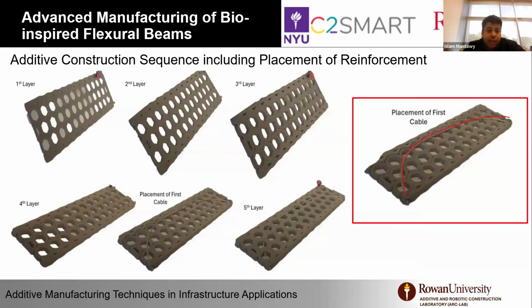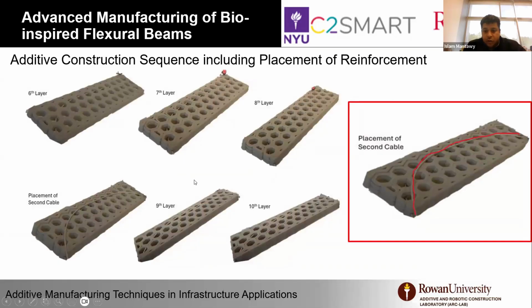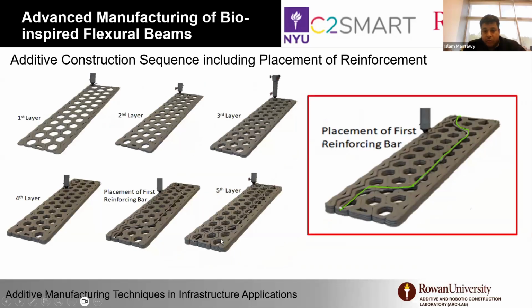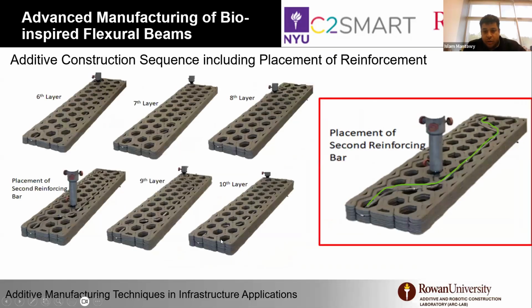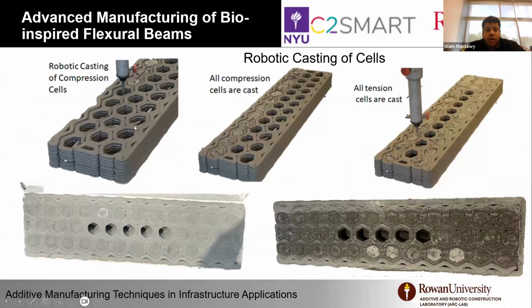So layer by layer, you can see printing one layer, next layer, third layer, and after that placing reinforcement, printing on top of it, completing the structure. This also allows us to print with rigid rebar, which I'm going to show later on. So basically you create these layers and embed the reinforcement. And at the end of the printing, the same printer changes the rheology of the material to be flowable and selectively fills the cells immediately after printing, not waiting.